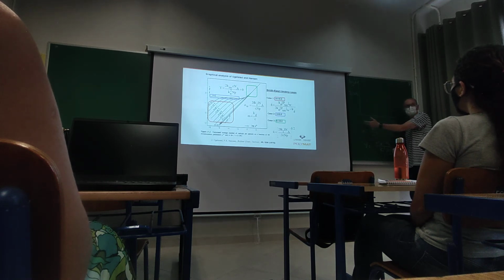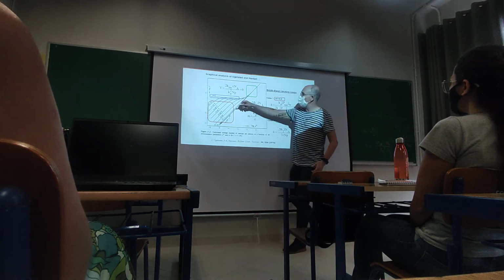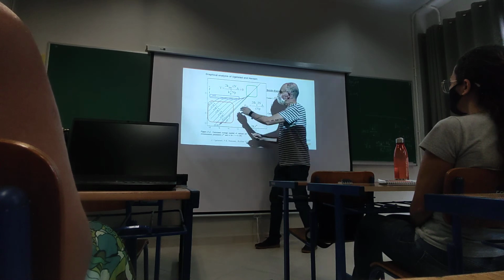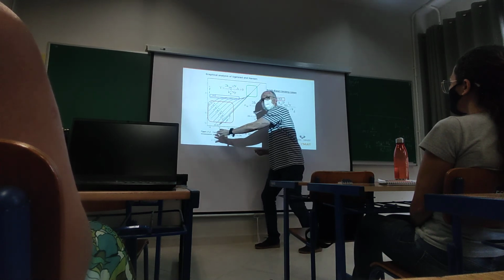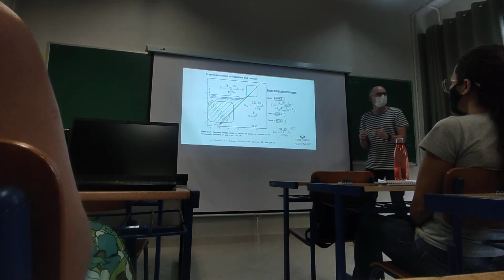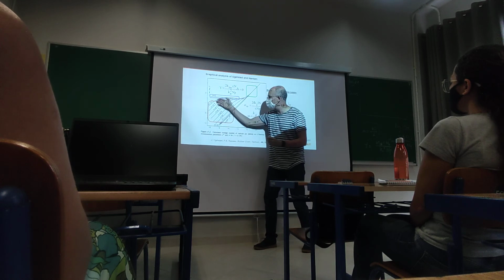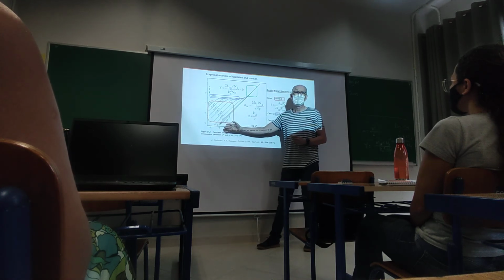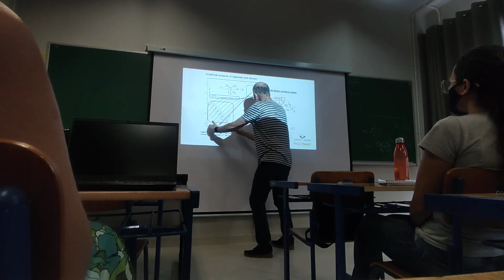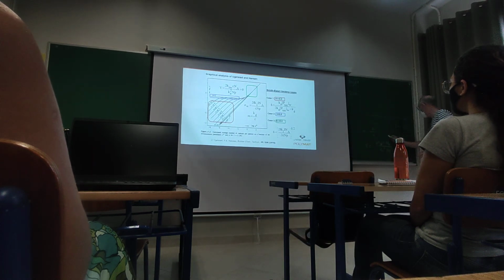When N increases, that means that exit starts to compete with termination of radicals in the polymer particles. Okay? So what you see is that if N increases, desorption increases, the lines go to lower values, so that M bar decreases. Okay? When desorption is important, the number of radicals per particle is below 0.5, well below 0.5. Okay? And this occurs in a large range of values of radical concentration in the aqueous phase.